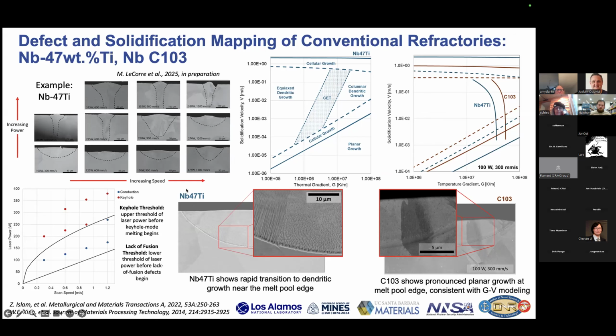So here for the niobium 47 Ti, if we zoom in on the edge of the melt pool, we tend to see a rapid transition to dendritic growth at the melt pool edge. And if we look at where that is relative to our map, that actually tends to make sense. Whereas if we look at C103, we tend to see planar growth at the edge of the melt pool as shown here. And that is consistent with sort of where we are in terms of the processing map as well.